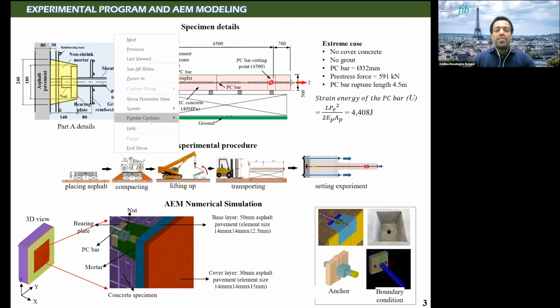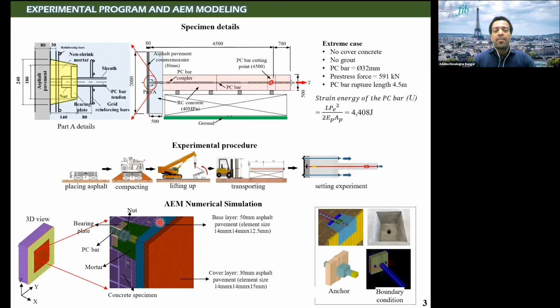So this is the experiment program and numerical modeling. The specimen is here. It consists of two RC members, this part and this part. They are reinforced concrete and connected together by a main bar at the center and two additional PC bars. Inside the sheaths, there is no grout. Cover concrete is 0 to simulate the worst scenario in practical case. Bar diameter is 32 millimeter and tension force is 591 kilonewton applied here. The bar is cut here, 4.5 meter from the PC bar head, and in this case, the strain energy of the PC bar is around 4,400 Joule.